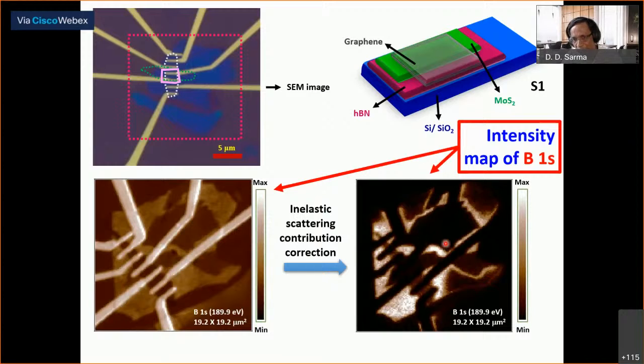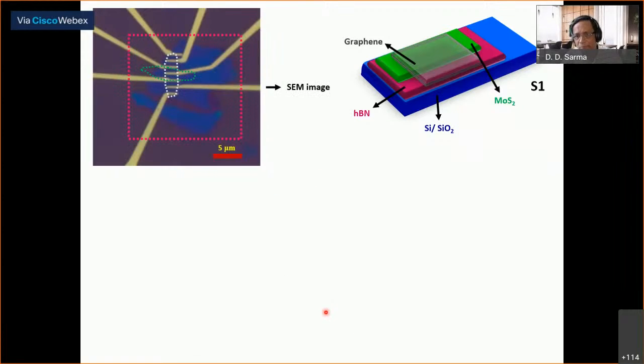This dark part where you don't see boron is where the molybdenum disulfide is sitting. And in fact, this shaded part you can see here, where you can see a little bit of the boron like this, that's a graphene piece sitting. I can take the carbon signal and I'll see only the graphene then, and I'll see the molybdenum 3d, and that is what I'm going to show you next, map of molybdenum 3d.